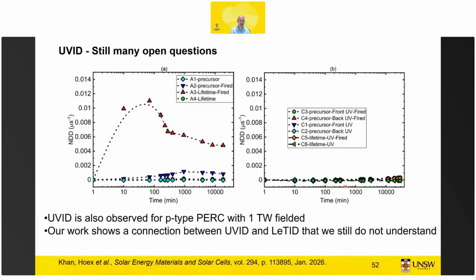There are still many open questions for UV-ID. This is one that we published earlier this year, where we showed an interesting correlation between light and elevated temperature-induced degradation. I'm sorry for the bad news: LeTID is still present. It's also present in TOPCon. It's not the dominant defect, but certain process conditions can trigger it. Of course, we know it's present in PERC modules, and we have 1 terawatt of PERC modules fielded. So it's a relevant topic. We see that without UV we see LETID, and with UV exposure we see no LETID in these samples. So there is a strange interaction which we have to understand in order to really ascertain what the fielded PERC modules will actually show in terms of degradation. It's a lot more complicated than we thought.